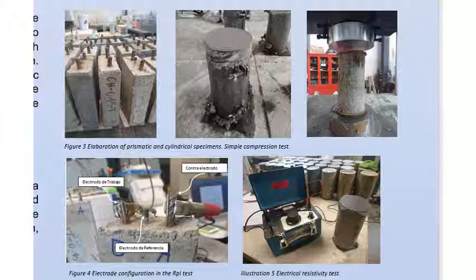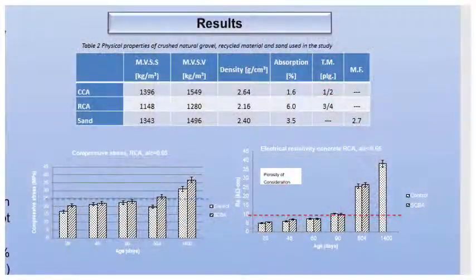The specimens were subjected to wet-dry cycles in water with a concentration of sodium chloride at 3.5% by mass. Corrosion potential and polarization resistance were measured. A Gamry potentiostat was used, evaluating with the technique of linear polarization resistance.